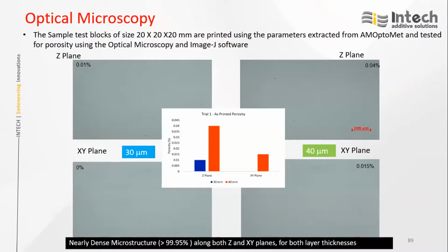Initially with Optomet we took process parameters for 30 microns and 40 microns, and both gave good density with porosity levels less than required - we got density of 99.95%. Finally we chose 40 microns over 30 microns because of productivity - 30 microns has more layers for a given component, so the printing time is longer. We got similar properties for both layer thicknesses.